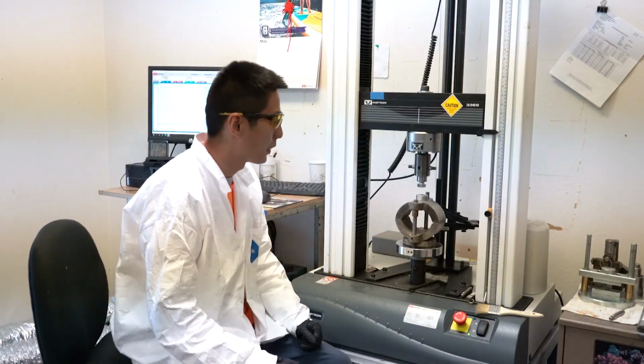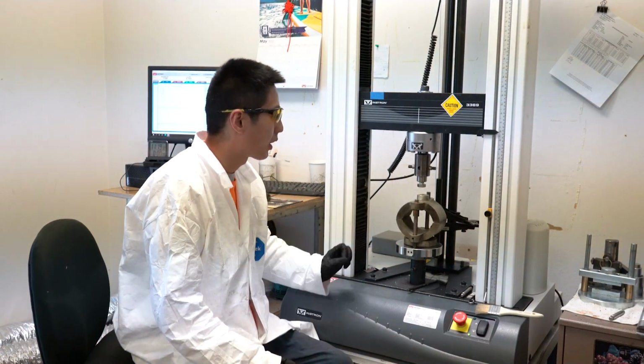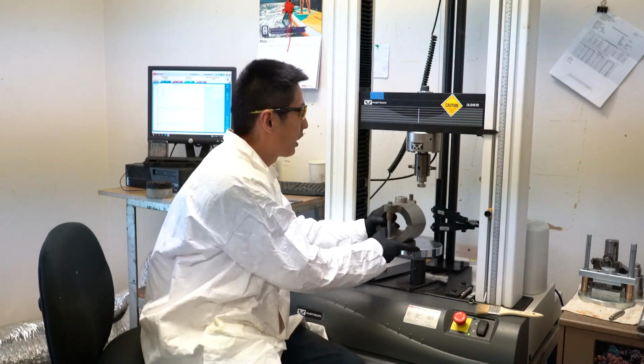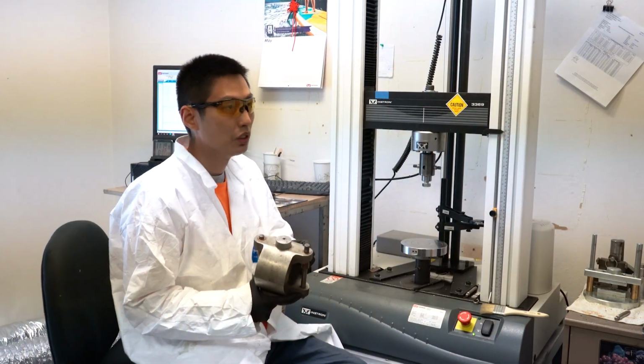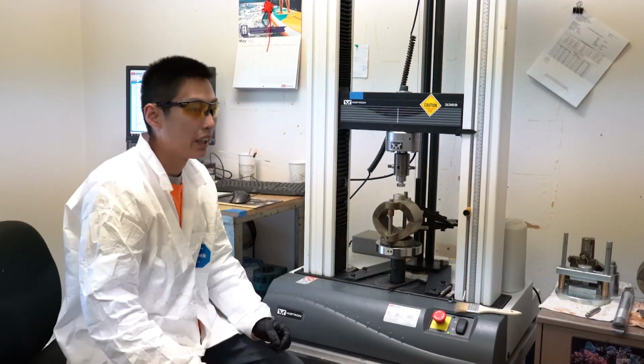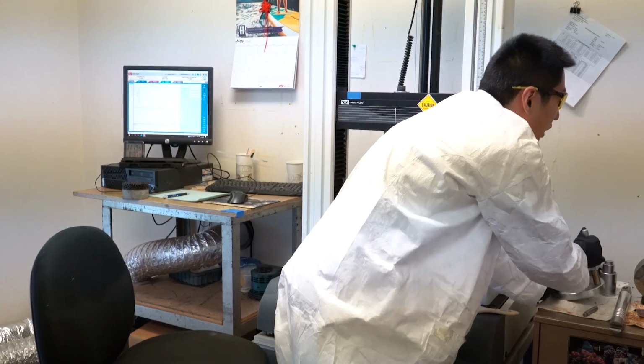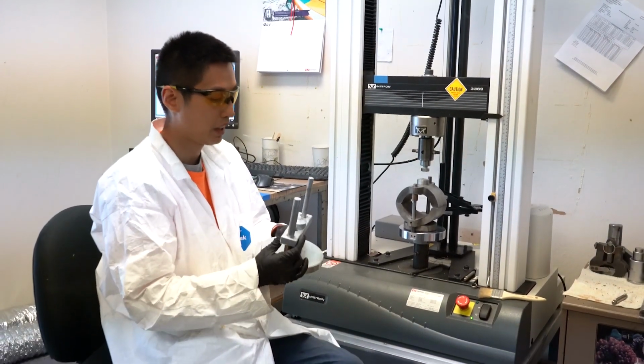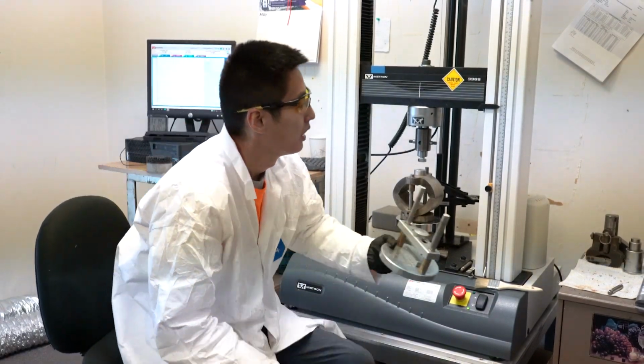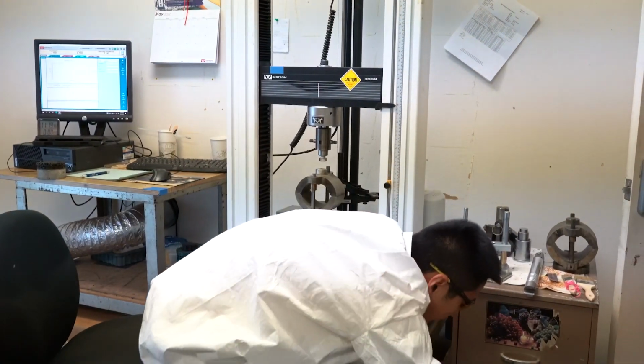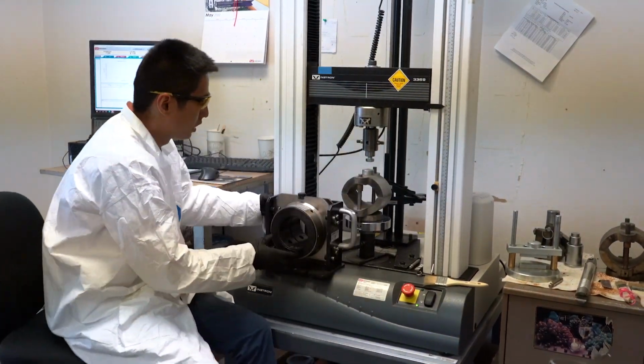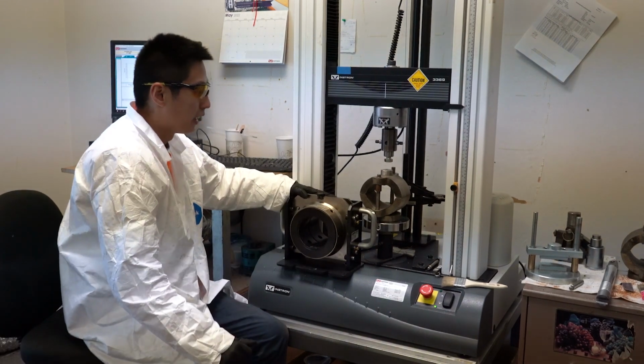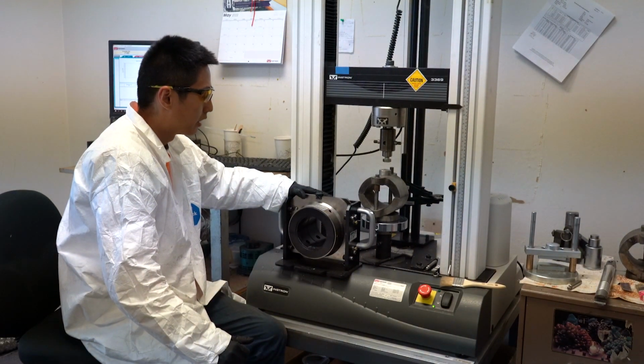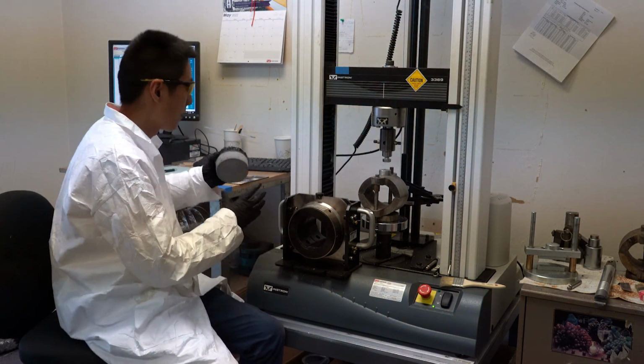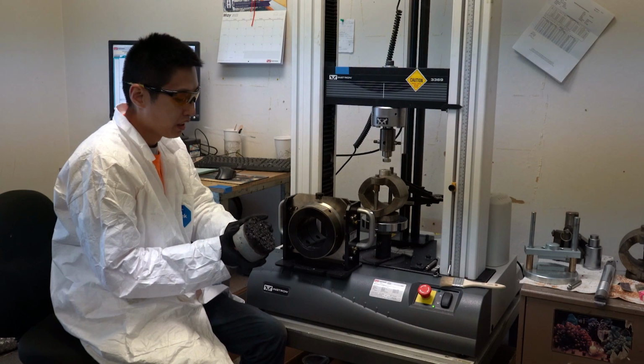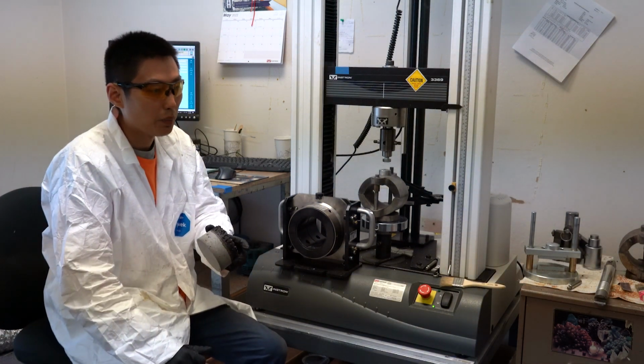This is our Instron machine, and from here we do the compression and also tensile test. And later I will show you the AASHTO T245, which is the Marshall stability we made earlier. And besides that, we have the split head, indirect tensile split head for AASHTO T283. And from there we have some other testing heads. This is for the interface shear test to test out the interface bonding strengths for our epoxy B1F epoxy asphalt.